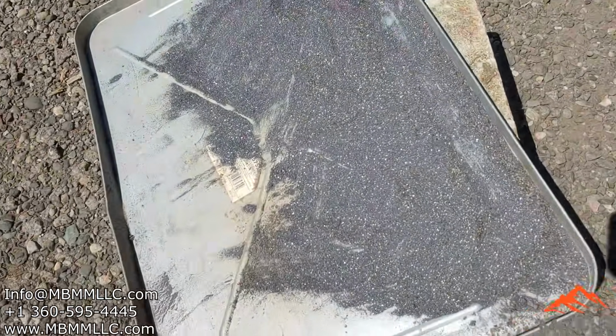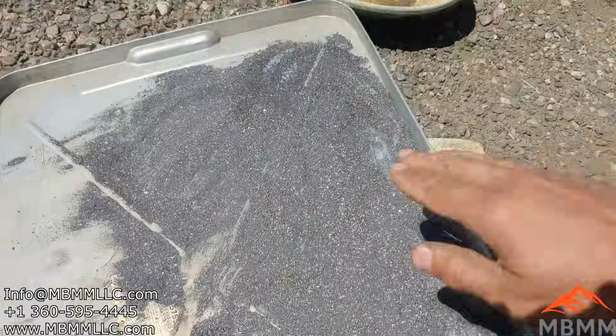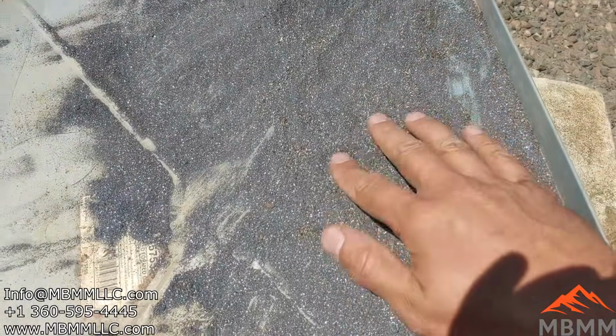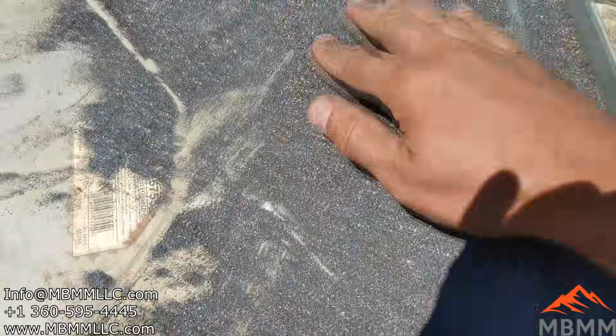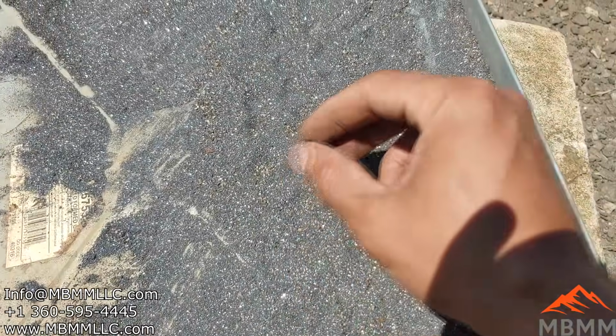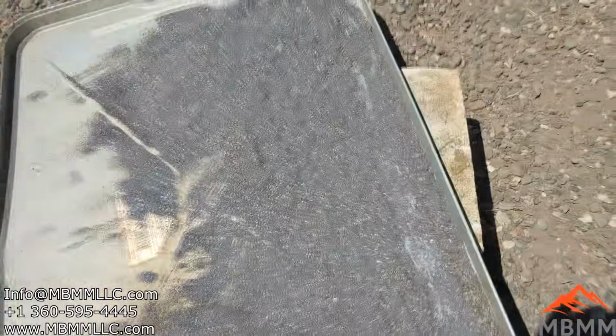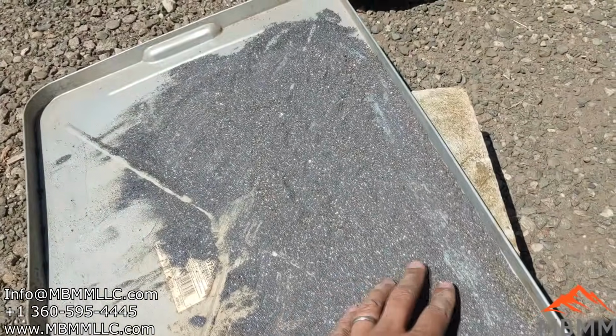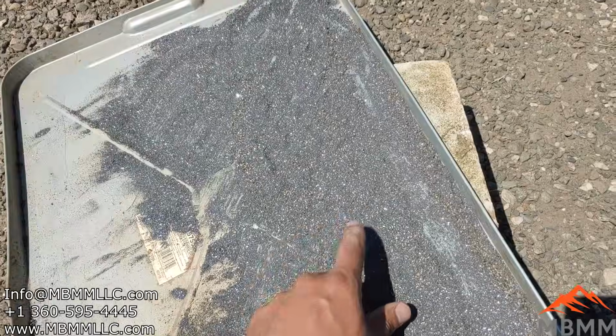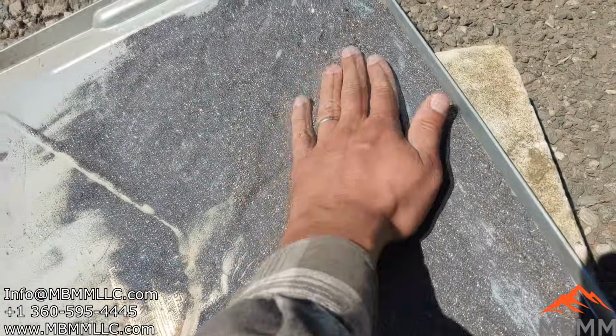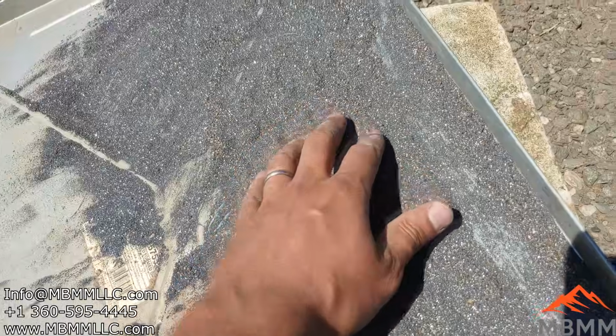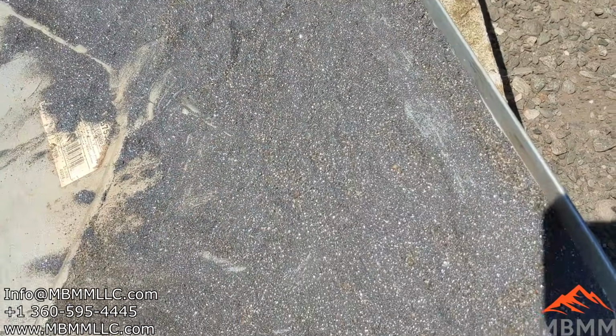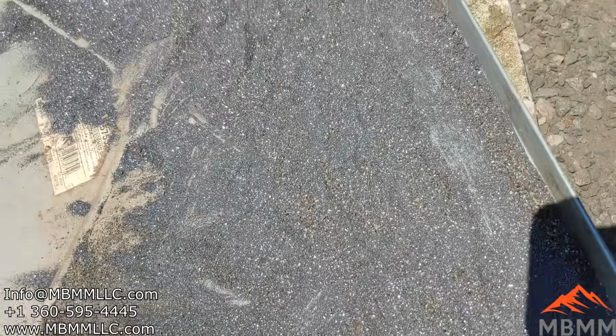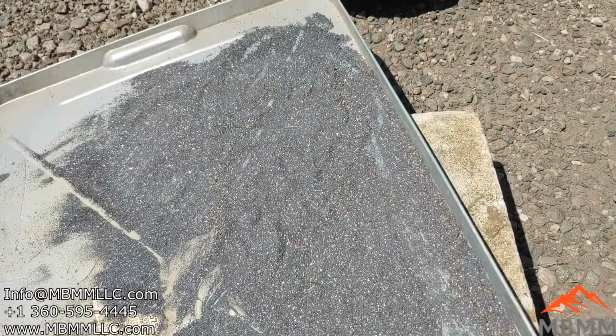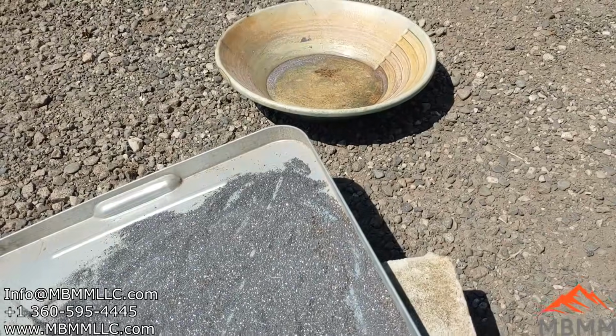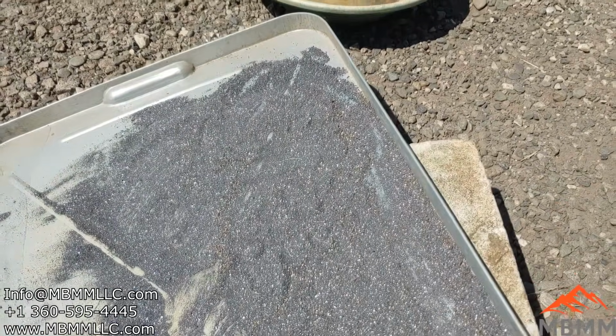Okay, here's our nice dried out galena, and usually you can tell it's dried out when there's no clumps in it. All the individual grains are moving around against each other. When it's still wet, it'll form little balls and clumps. And we dry it out for 2 reasons. One is so we can get an accurate weight when we're mixing up our flux, but also one time early on, I did a smelt with some wet material, and the crucible actually blew up in the furnace. So I like to get it real nice and dry now, so I don't have any explosions. So we'll get it put in that pan, and we'll get it inside and get some flux weighed up and get this smelting.